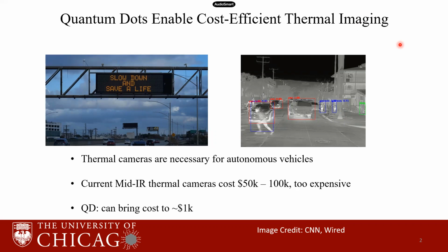To solve this problem, our lab at the University of Chicago is developing thermal cameras using quantum dots. The main benefit of these quantum dots is that they are very cheap to fabricate. The current materials to make thermal cameras are mercury cadmium telluride alloys, which are made by molecular beam epitaxy, which makes them very expensive. In comparison, quantum dots can be made by a very simple chemical synthesis, and this can bring down the cost to around $1,000 and revolutionize this technology.